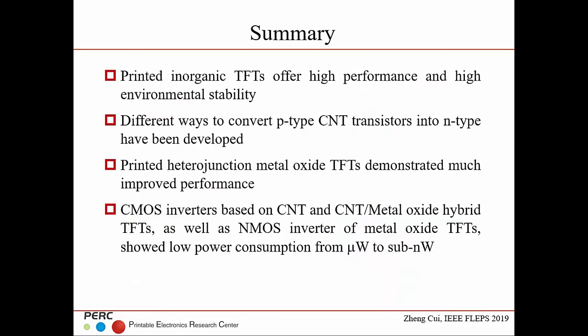So in summary, I'm showing that the printed inorganic TFT offers really high performance and high environmental stability. Also, showing different ways to convert the P-type CNT transistor into N-type. And also, I showed the heterojunction TFT, which gives the oxide TFT much better performance. And we showed different ways to make N-type, so that you can construct the CMOS inverter, which gives you low power consumption from microwatts to sub-nanowatts.